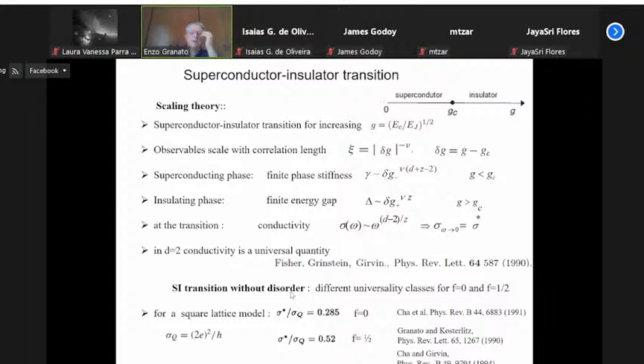The scaling theory for the superconductor transition states that there is a critical value for the ratio of the charging energy to the Josephson coupling, where the transition occurs between superconductor and insulator. There is a divergent correlation length, which depends on the distance to the critical point, and the measurable quantities or observables should scale with this correlation length. So in the superconducting phase, the phase stiffness is finite. The phase stiffness measures the stiffness of the phase coherent state, the energy cost to actually untwist the phase.